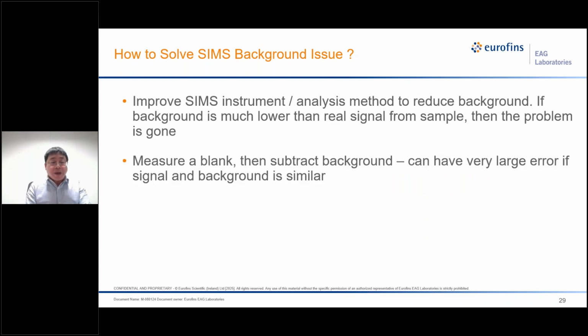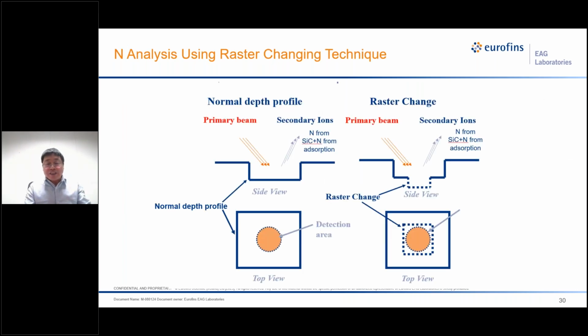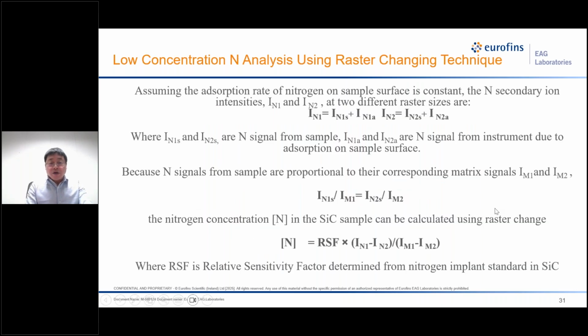Another method is to measure the background, then do the subtraction. This will have larger error if the signal and background are similar. The third option is raster change. I'm not going to talk about the details here, but I just want to point out that in the same profile, we can change the raster size and increase the beam density, and then we can collect the signal at two rasters, the regular raster and the smaller raster. The conclusion here is, by using the raster change, we can remove the background contribution.